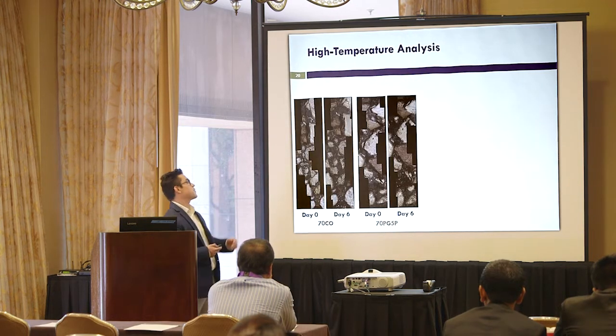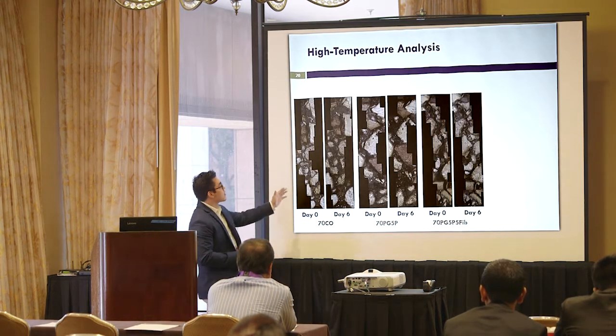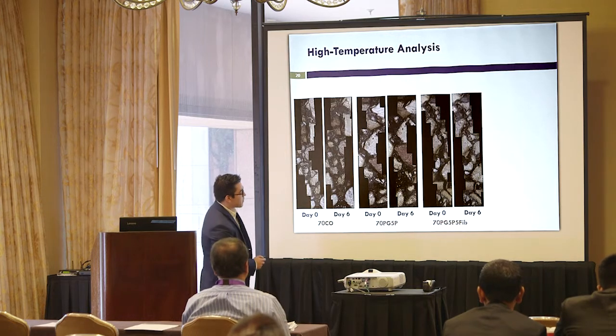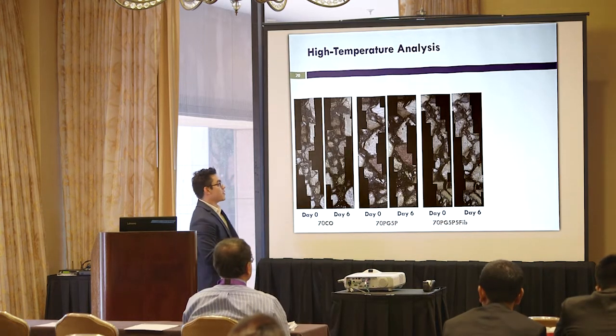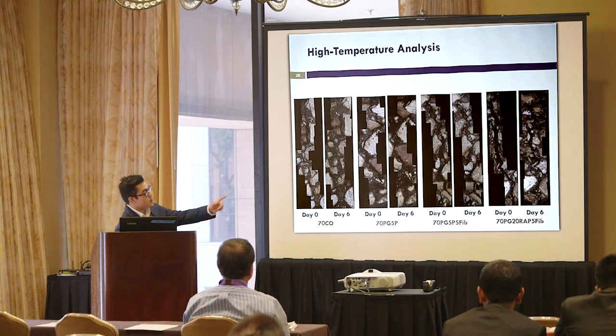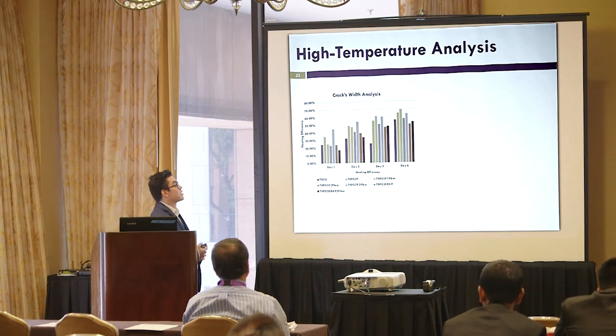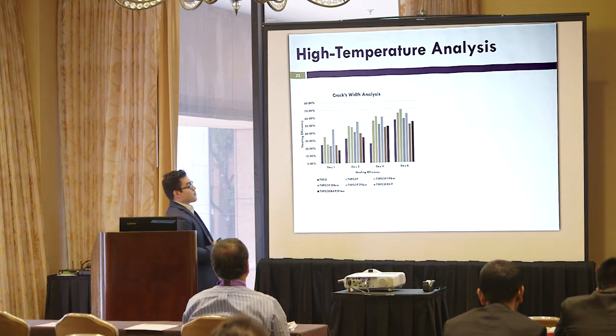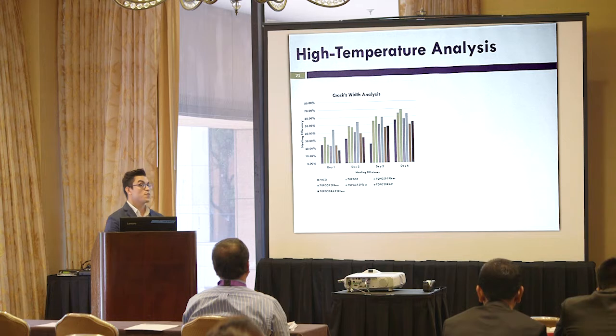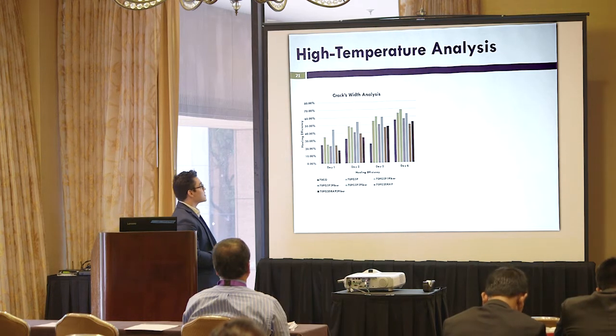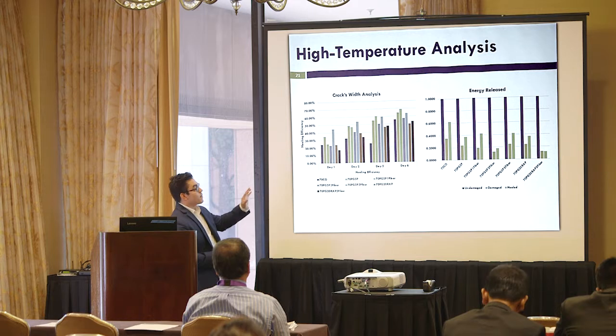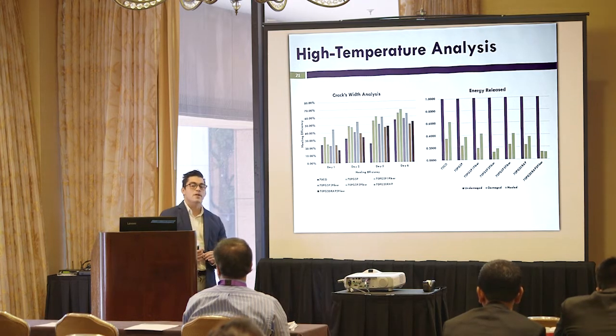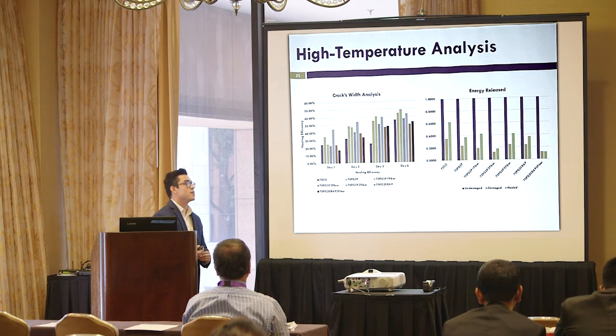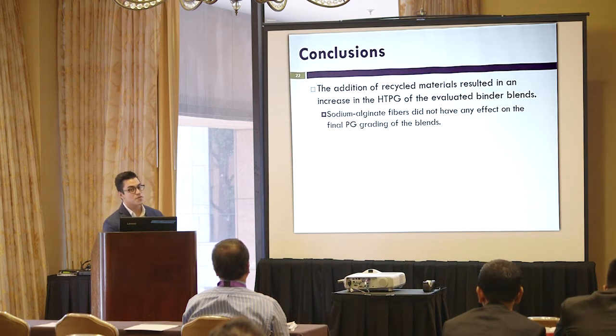And we have the same pictures for the high temperature environment, and you can also see 5% fibers plus 5% RAS. The crack width gets really small again, and also with the RAP, you can see a reduction in the size of the crack. And for this particular healing environment, the mixture containing 5% RAS plus 1% fibers had the highest healing efficiency based on the crack width, and it also had a good recovery of strength based on the energy release analysis. So in conclusions, we observed that